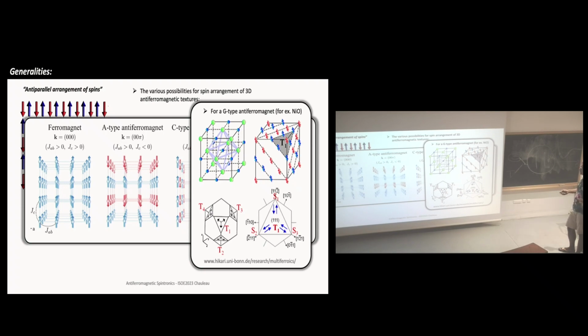And then you see, if you take the example of NiO, which is an archetypical G-type antiferromagnet, basically you have all these 111 planes, which are ferromagnetic like this, and then antiferromagnetically coupled. But if you look at this, basically you have 4 possibilities to stack them. So that makes 4 T domains. And among these T domains, you have 3 possible orientations. This is what we call the S domains.